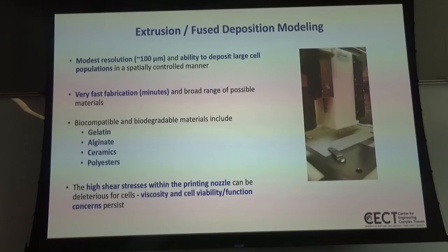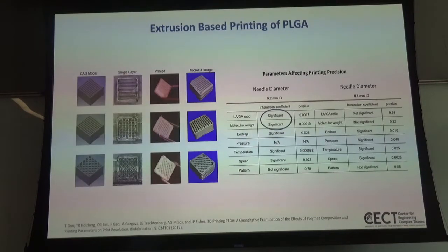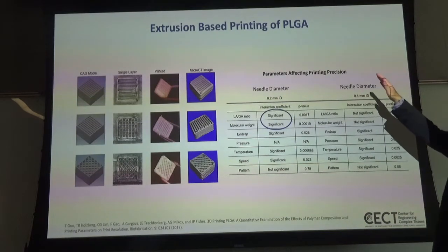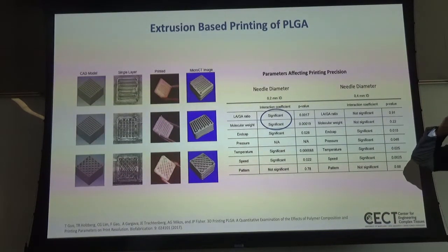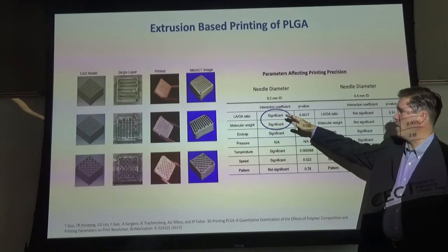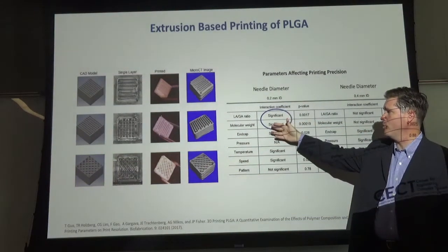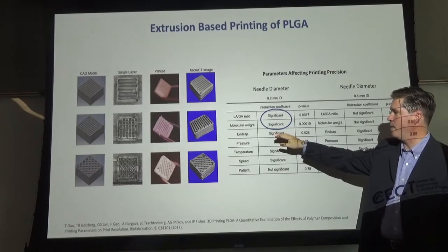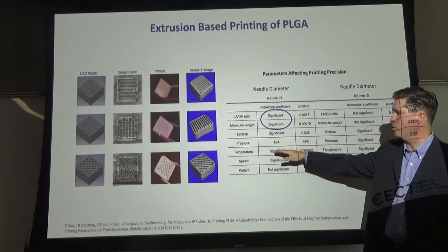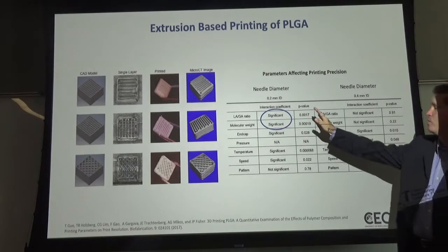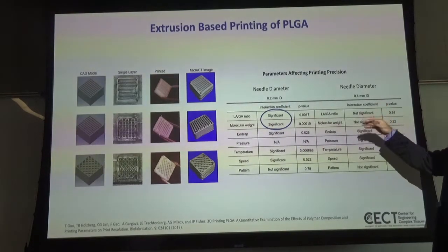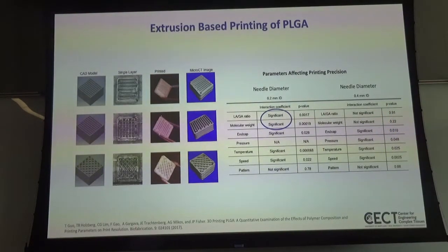So similarly, we've done some studies to characterize these approaches in extrusion-based printing. In this study, we looked at just simple extrusion printing of PLGA. We looked at a variety of chemistries, so copolymer ratio, molecular weight, end-cap chemistry, as well as printing conditions, pressure, temperature, speed, and pattern. And we did this for multiple needle diameters and just asked the simple question of what's the fidelity of what we're getting when we print an object compared to the design of that object in CAD.